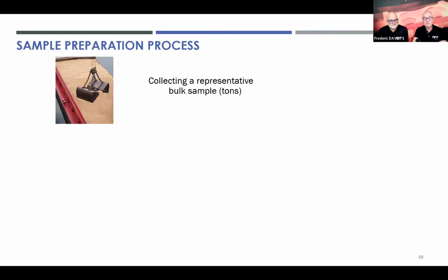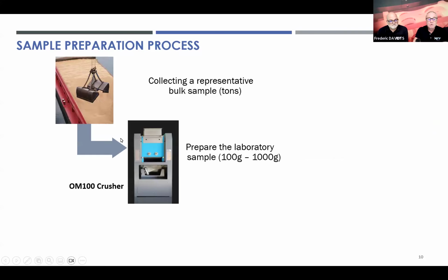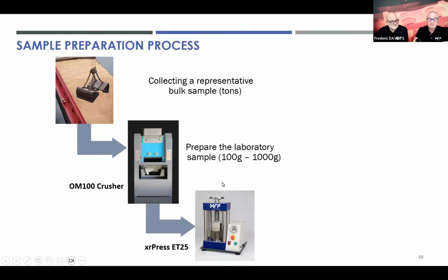Now, if you look at the sample preparation process, first of all, we have to do the sampling. The sampling can be, for example, a shipload, and we need to collect a representative sample for that bulk material. This bulk sample is in general many tons of material. So we need to try to obtain a laboratory sample that is representative for this bulk material. From those many tons, we go to a sample that contains maybe 100 to 1,000 grams, which goes into the laboratory where we use equipment that XRF Scientific has available to reduce the sample to the right size, but also to have a representative sample.